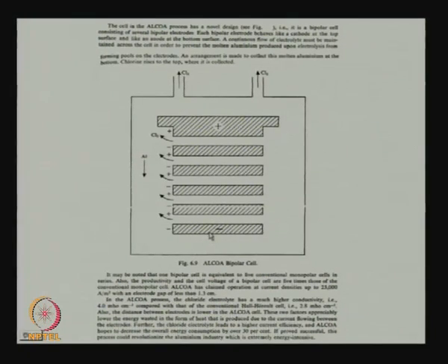So, this is the cathode which draws aluminum, but aluminum is drawn everywhere on the cathode side, and after the aluminum ion gets discharged, it falls down to the bottom. So, at the bottom aluminum collects. And the plus side means the anodes, chlorine is liberated. It is liberated here, here, there, there. All the chlorine being liberated will come out from here. Now, these electrodes are called bipolar electrodes. I mean the same piece of graphite is serving both as anode and cathode.